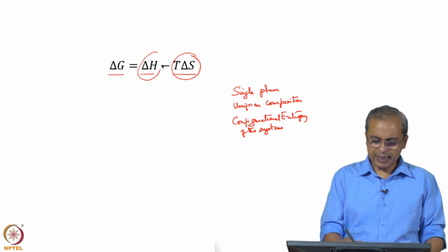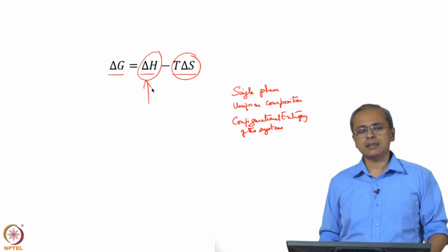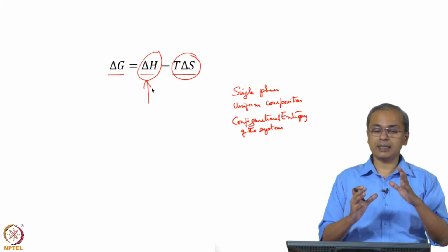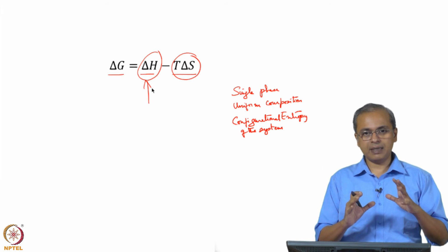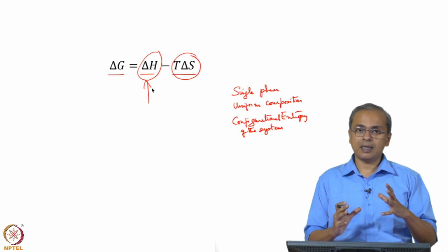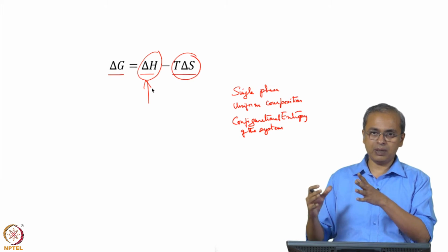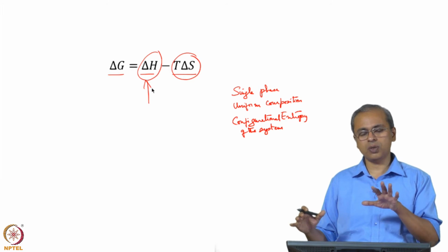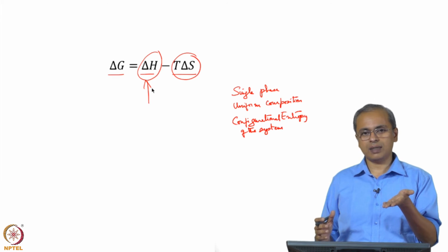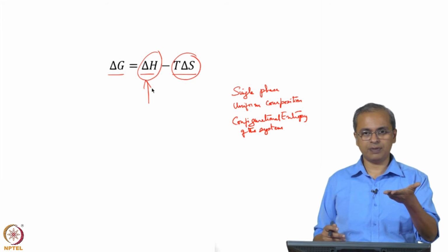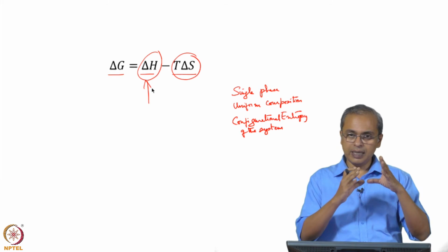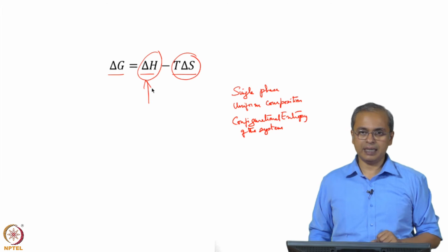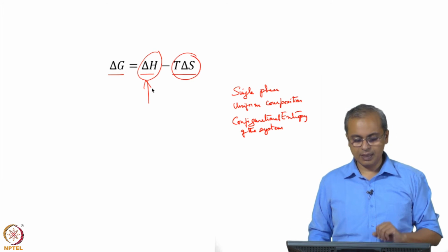On the other hand, it turns out that delta H, the enthalpy, has a significant dependence on the crystal size, and this is something that we need to understand. At large crystal size the crystal size dependence reduces to 0 and then you only see the delta H of the transformation between one phase and the other phase. When you go to smaller crystallite size, you see the same transformation delta H still being present, but you also have a crystal size effect showing up in the delta H, and that affects the outcome.